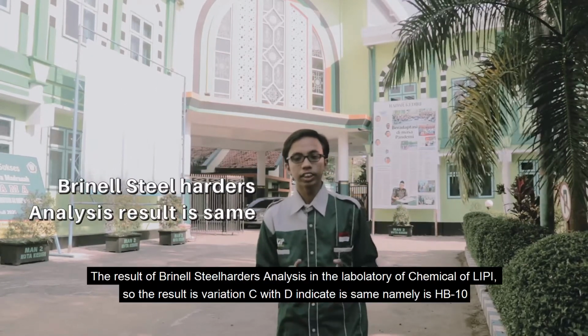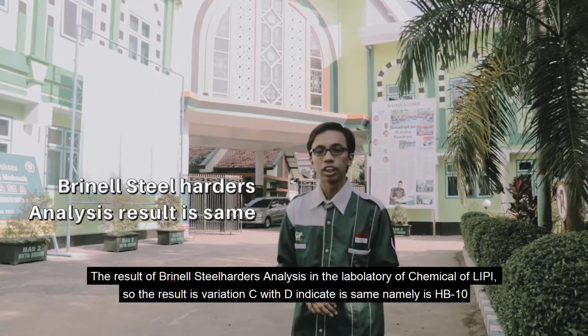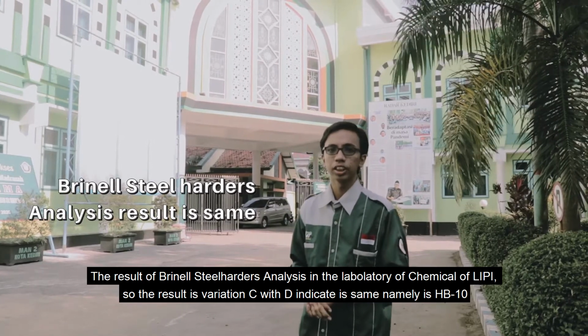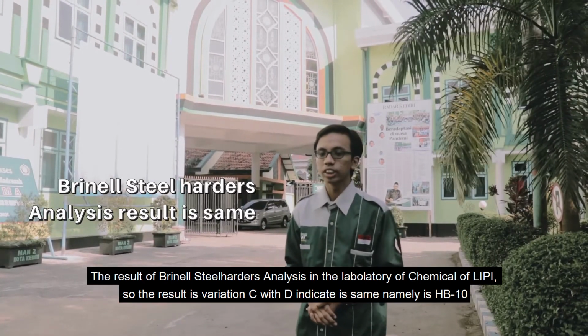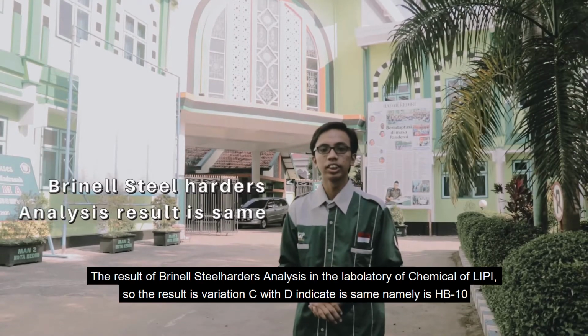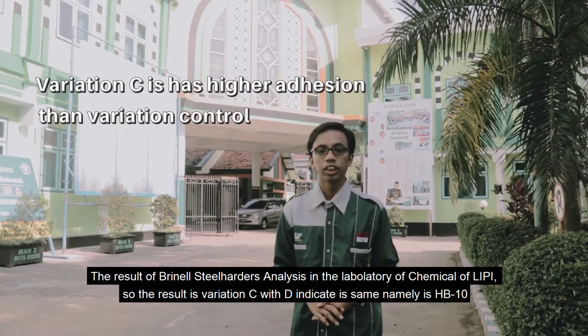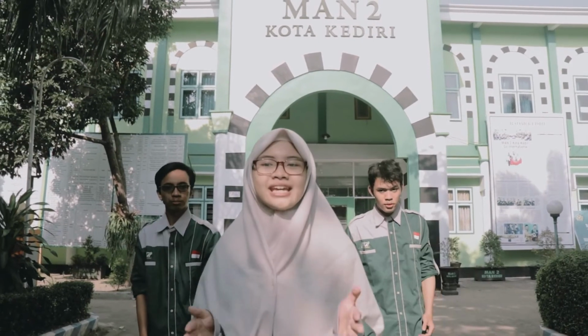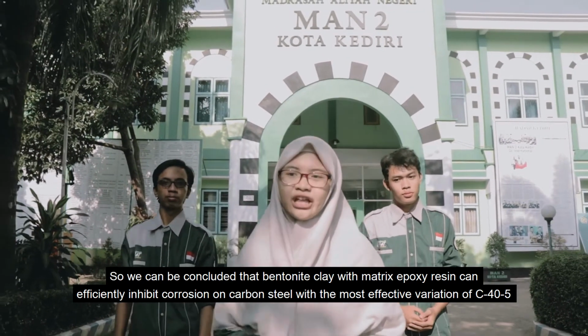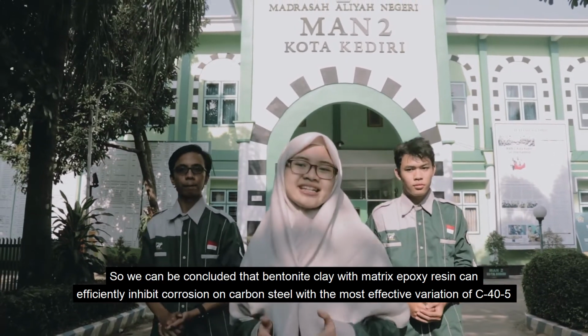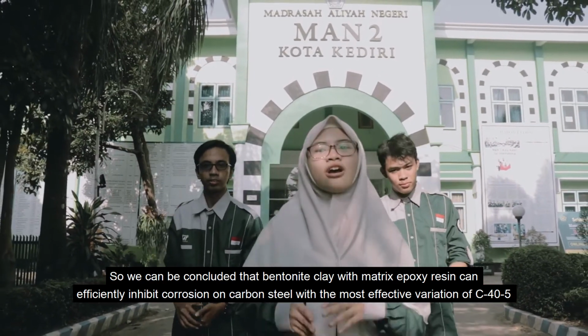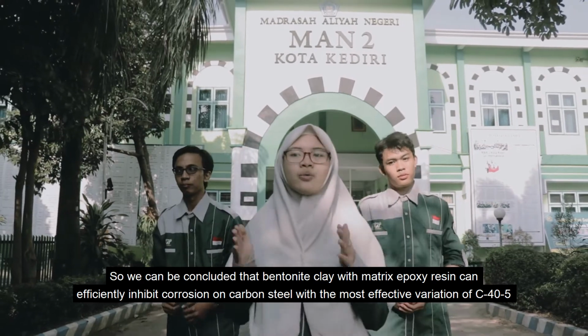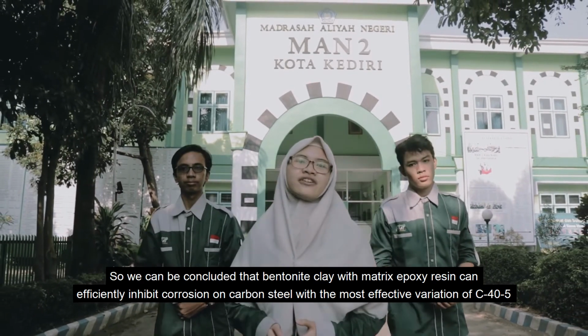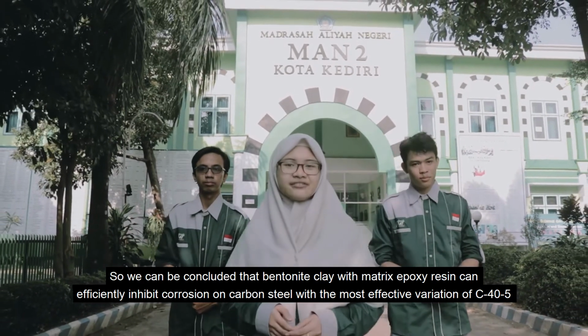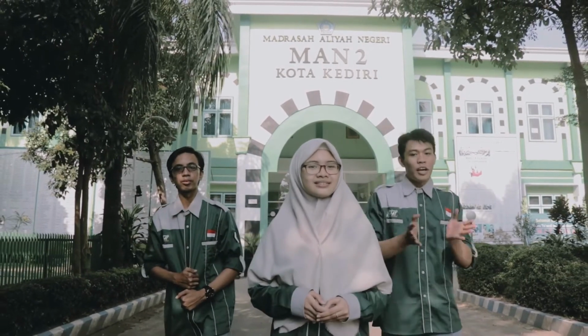The result of the Brinell hardness analysis in the chemical laboratory of LIPI shows variation C and variation D have the same result, namely HB10. So, we can conclude that bentonite clay with epoxy resin matrix can efficiently inhibit corrosion on carbon steel, with the most effective variation being C-40-5. Alright, thank you very much.